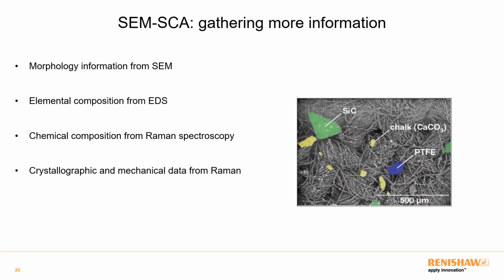Here I have a simple example of why it's useful to have Raman in conjunction with SEM and EDS. On the right-hand side we've got an image of a series of fibers, and on top of those fibers are a number of different particles, all of different chemical composition. Now EDS enables us to get elemental composition of these particles. For instance, it will be very good at identifying that we have silicon carbide here. However, if we go to the PTFE particle, when we do EDS, we will just see elemental carbon. Now, that's clearly not that useful. However, if we take a Raman spectrum from the same particle, we will get a Raman spectrum of PTFE, which we can simply run through a database, match it with PTFE, and we've got a confirmed chemical identification.